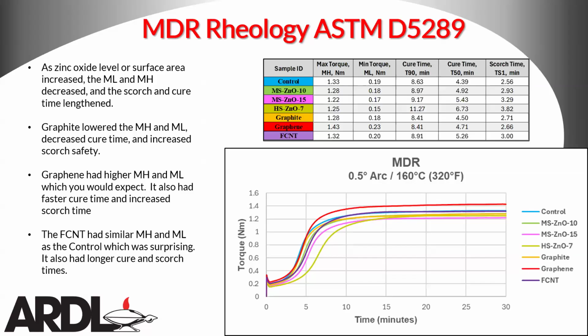And we're going to talk about some of the things that we found, that some of it's surprising, some of it isn't. But as your zinc oxide level or your surface area of the zinc oxide level increased, the minimum and the maximum torque decreased, which was a little bit surprising because since zinc oxide is an activator, you would have expected maybe the maximum torque to go up a little bit. You also saw the scorch and the cure time actually lengthened. Once again, that was a little bit surprising because you would think, well, I should be activating my cure more, and we really didn't see that.